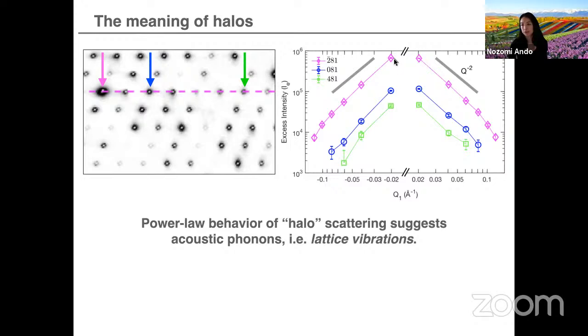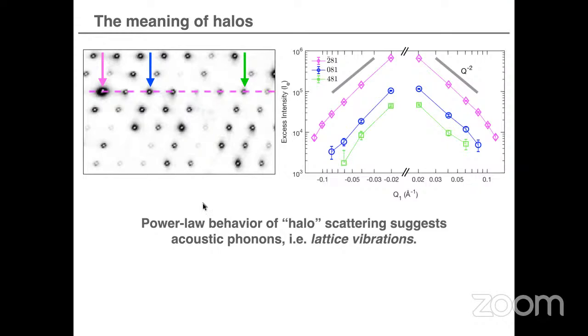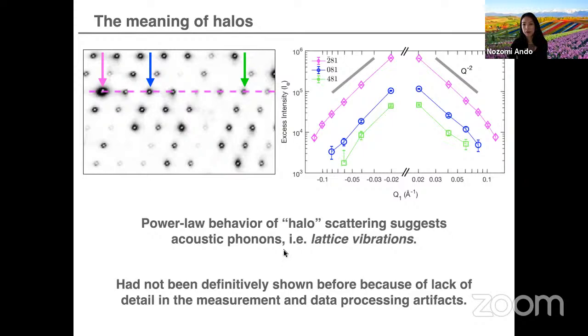And based on the position of the lowest angle peak, it's telling us that something like 300 angstroms of distance, so atoms are correlated over that sort of long distance, which is roughly 10 unit cells for this particular crystal. So long range correlations appear to be responsible for the halos. And this could also be demonstrated another way. Before I go on to explain that, I should say that the presence of halos had been proposed, actually by Peter Moore.